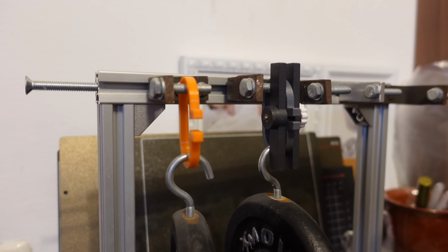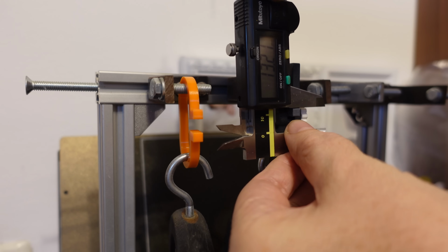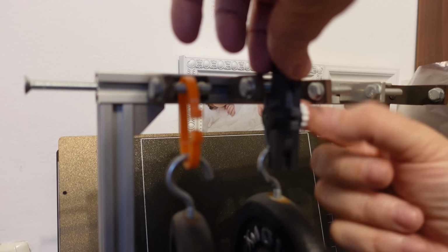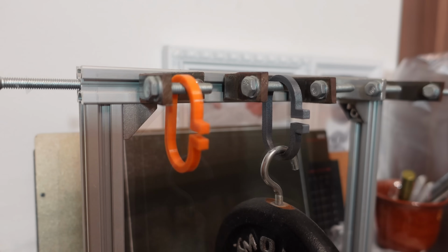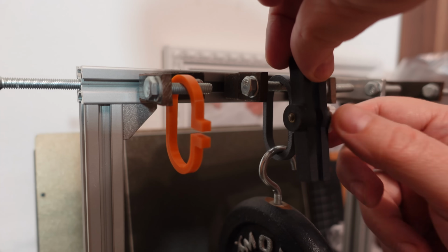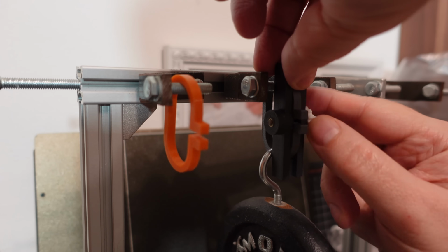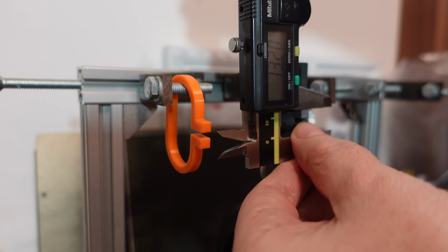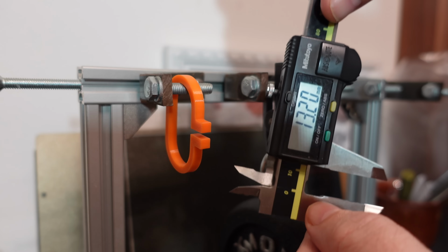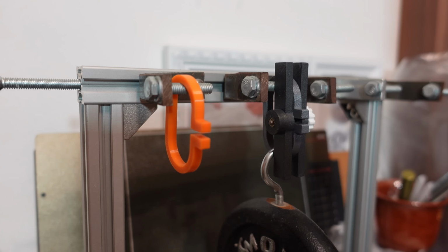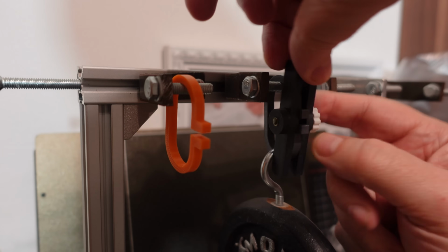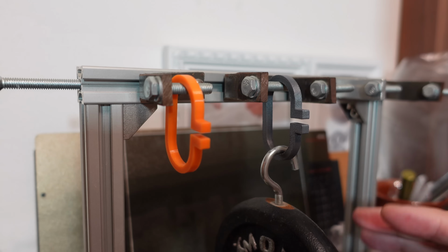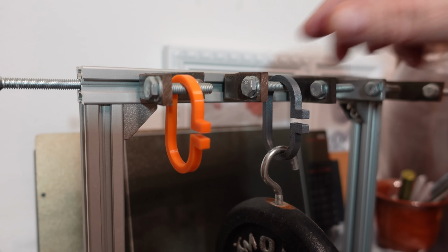Creep test, the deformation under constant load of 1.25 kg. Locking the position for more accurate measuring. 13.21 mm. So this is the initial deformation. And after 5 days, let's measure it again. Locking the position. 13.20. Less than the start deformation. Absolutely no creeping, not even on day one.